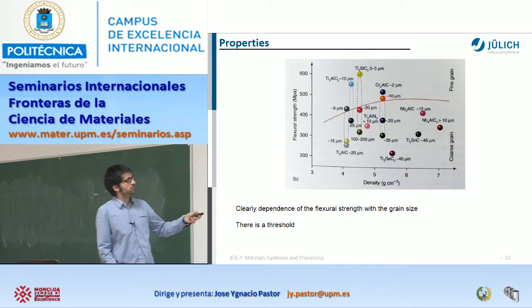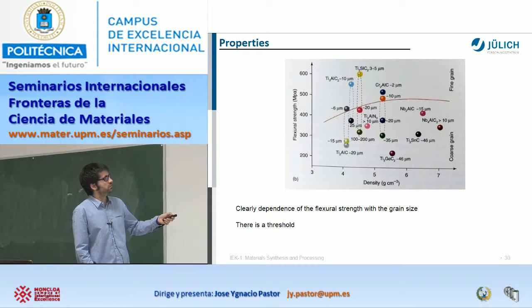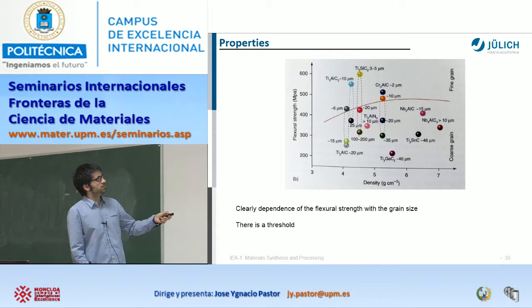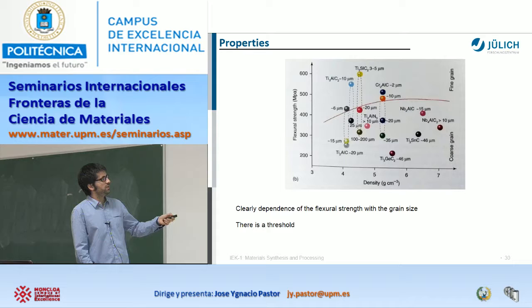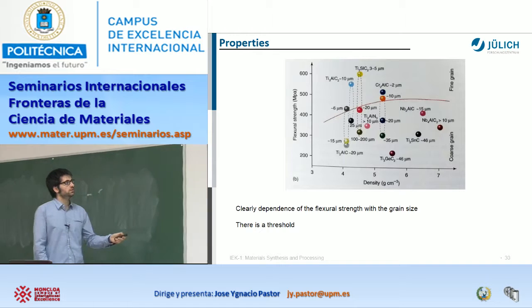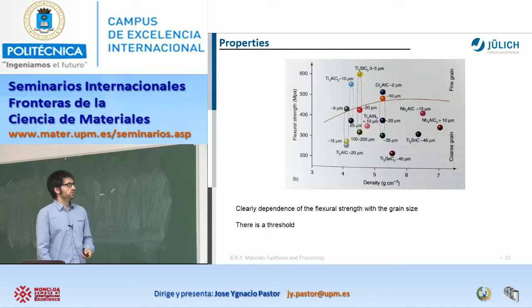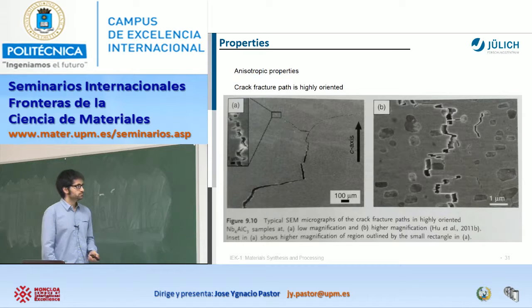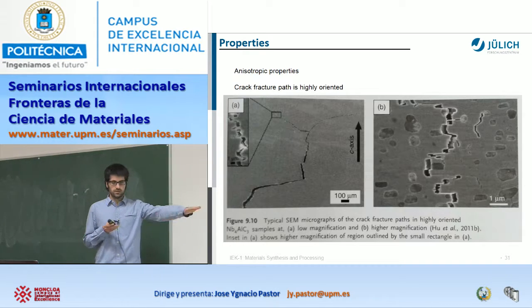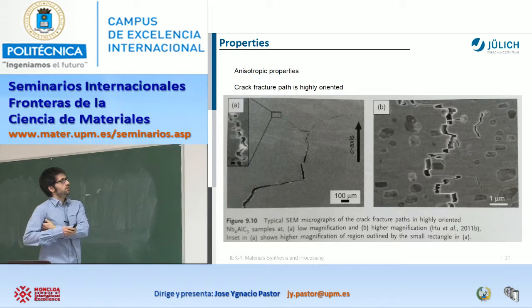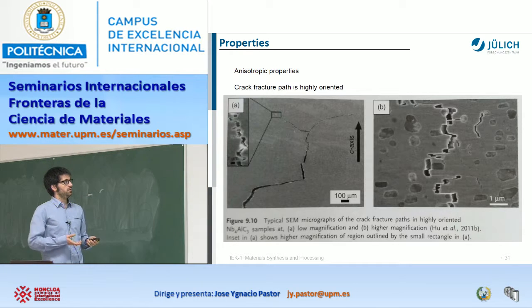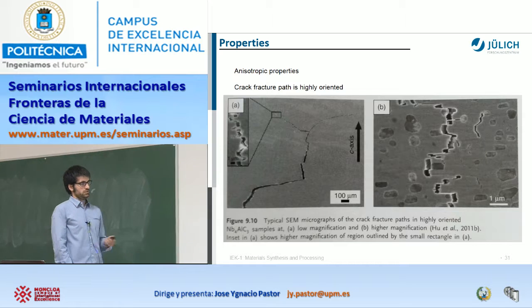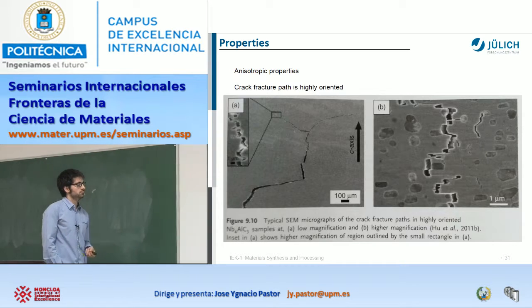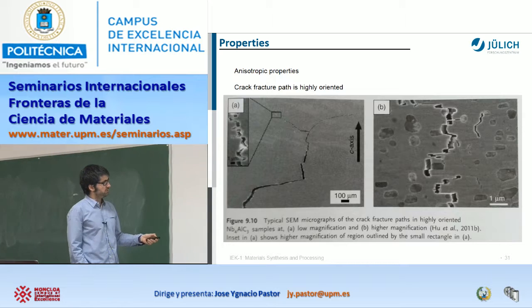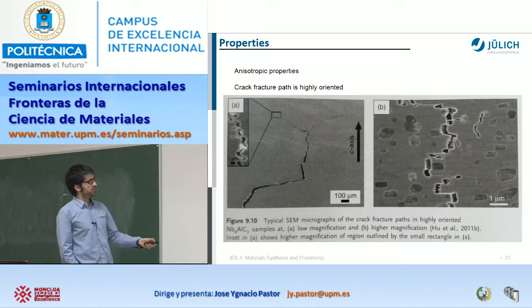Okay, to compare this material with that one, here is 10 microns of mean grain size, or here 25, and it's obvious there is a gap. If you need larger flexural strength, you should go for the small grain sizes. And here is one of the samples with layered structures. The crack fractures can be stopped. Even the fracture toughness, as I told you, has been measured up to 20, and it is for this reason. I mean, you can deflect the crack readily all the time.